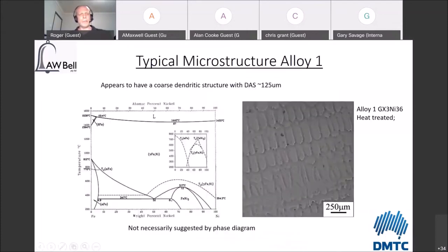Now, one of the things that I do have to mention about the Invar material, it has a very, very interesting solidification behaviour. When you look at the microstructure, and you can see this is a picture on the right-hand side of alloy 1, it's got a reasonably coarse dendritic structure. There's various small bits and pieces in the microstructure which are residue from the fact that we are air melting this material. We use an argon purge throughout melting, but there are still small oxides that you can see. The way it's been etched does show these quite clearly in the microstructure, in the interdendritic regions in particular.